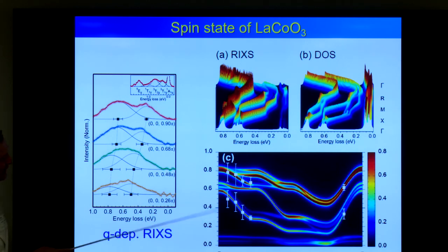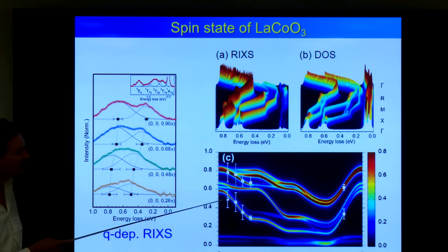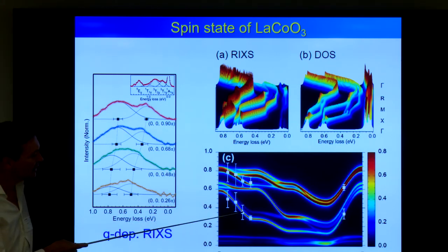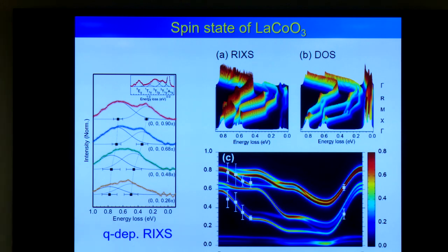These 4 points. So this would be an ideal experiment to repeat with better resolution. This initial experiment was with 100 millielectron volt. We repeated it now with 30 millielectron volt at ESRF. But it's a nice tool. So okay, this is very well known in cuprates, and then you have the magnons and the things. But you can also now start to think of doing that in open shell systems.